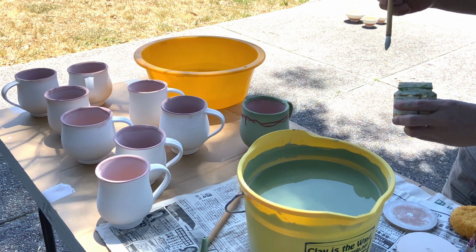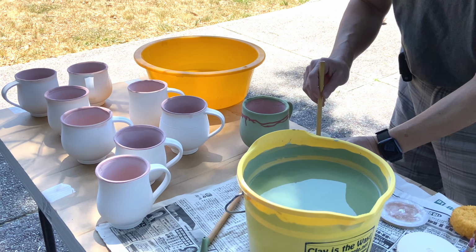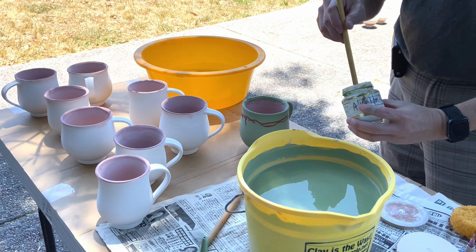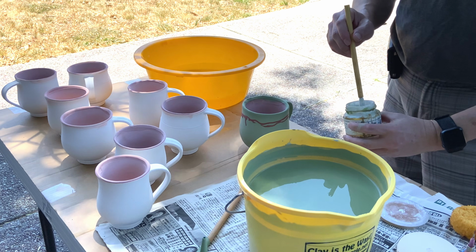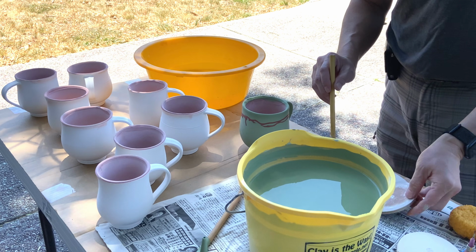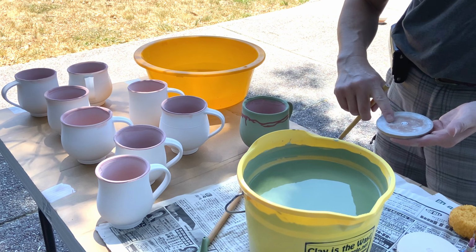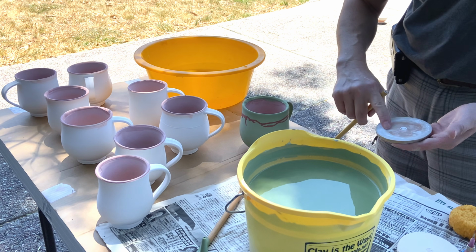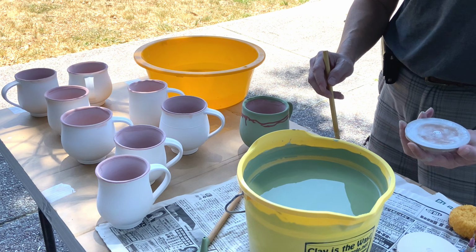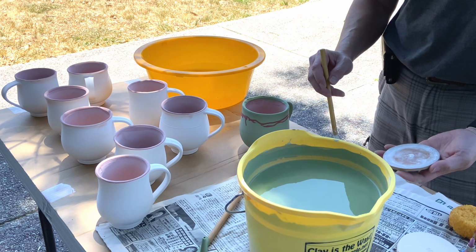So for applying the wax, this is the bottom wax. Okay, I told you in my previous demonstration, you just add aluminum hydrate into your wax resist. And after firing, you see that it becomes powder. These are all the powder that is left over. This piece of cookie has been fired already. You can recycle, reuse it.